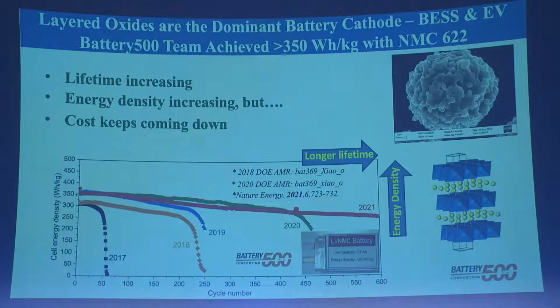But the numbers I show you here are real cells, and the cells are in fact tested at Idaho National Lab. So one place makes the material, another one makes the cells, and the third place does the testing. So it's totally independent. There's no one group saying, hey, I've got the greatest thing. So we work very much as a team. And I should emphasize the materials we use commercially today are what we call meatballs. You can see why, looking at that. Now, the primary particles are about 100 nanometers or so. The secondary large particles are anywhere from 5 to 20 microns in size. And these pack well. They're very good at making batteries, but I'll show you in a moment, they have some major problems.